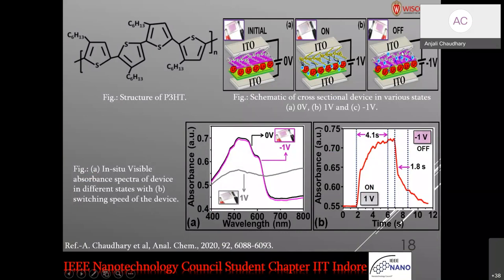We have fabricated a device using polythiophene in the manner that I discussed, that there are two conducting electrodes. Here we use ITO, and we apply a P3HT layer using spin coating, and then provide a lithium perchlorate electrolyte in between these two electrodes. And we see what happens when we apply some voltage, and we see there is a color change with the application of 1 volt, when you apply a positive 1 volt in a manner that the P3HT electrode is connected to the positive supply of the power supply and the other electrode to the negative. And when you apply -1 volt, it regains its initial magenta color.